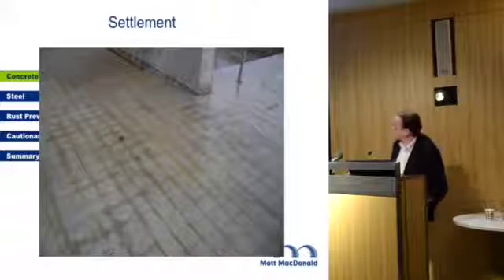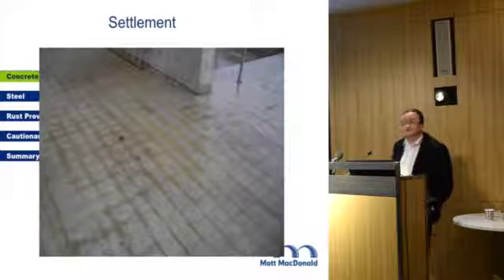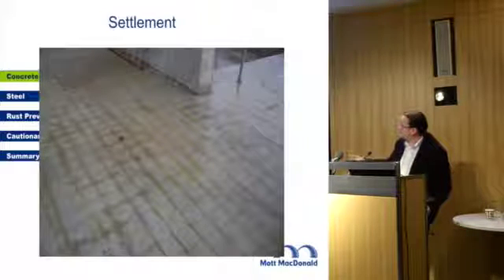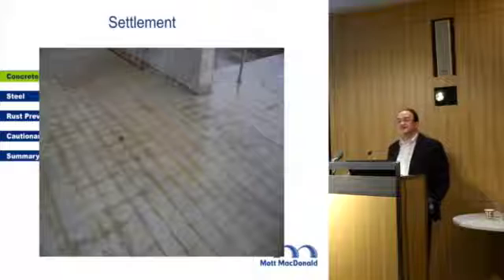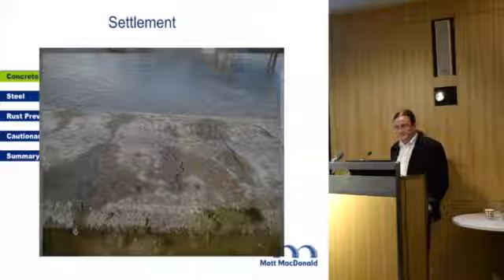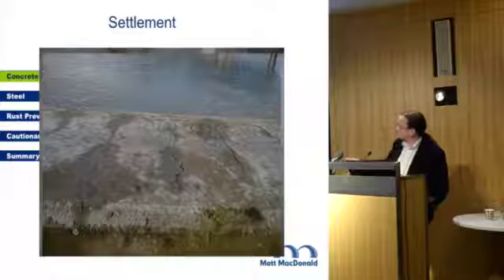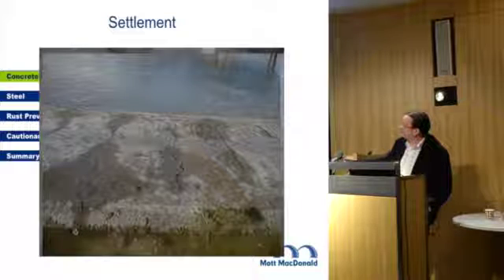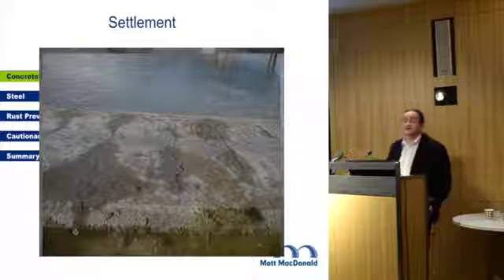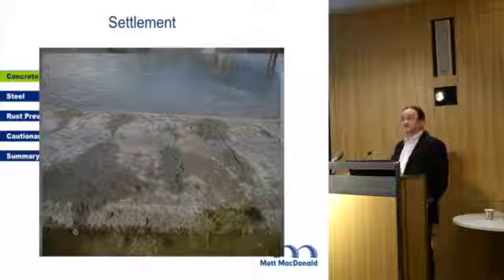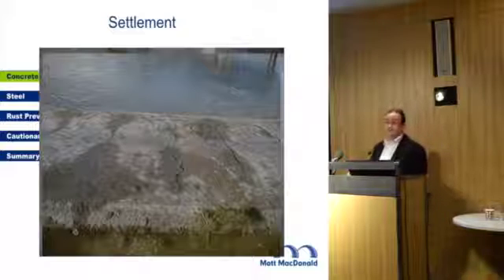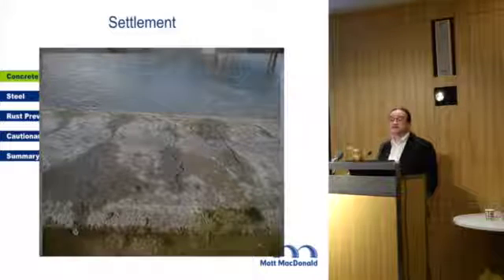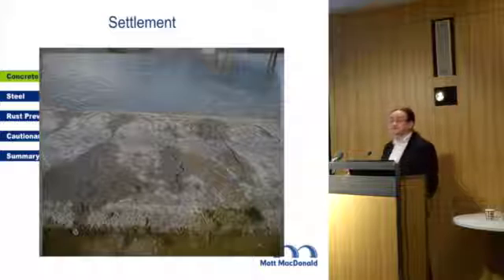Plastic settlement. Basically, concrete settles down when it's wet. You can spot where all the reinforcement is. Durability-wise, that might be a problem. This is a structure up in Scotland, in a water retaining structure, and you've got the same kind of thing. The bars are basically immediately underneath the cracks, which means the bars aren't in nice friendly concrete anymore. The bars are basically in the water that's collecting in the cracks. So they're probably going to give you a corrosion problem, and you need to do something about them.